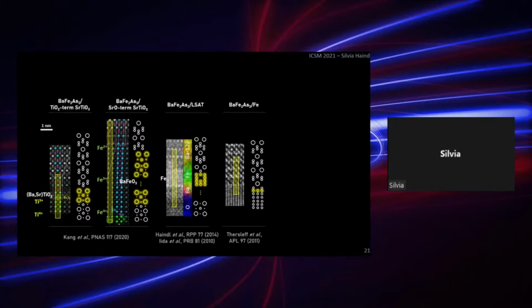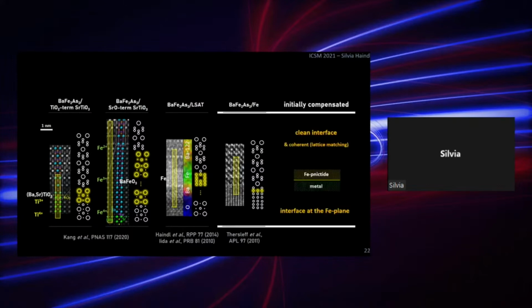And we can do that if you think about the example of barium 122 directly on iron. We see here that this is a clean interface, and the interface is located at the iron planes. There's a commonly shared iron plane. And this is not the only example, so we can call that clean interface an initially compensated interface, and it is also coherent due to the lattice matching.